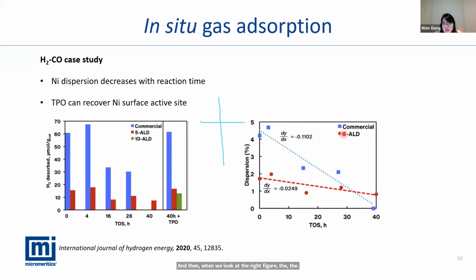So if we look at the commercial one, we are able to see after 40 hours of experiments, the nickel lost all the surface site. That means the nickel has either been sintering, so they lost all the surface site, sintering to very big particles, or has some carbon deposited on the nickel surface. So the customer also did a temperature programmed reduction, temperature programmed oxidation on the deactivated nickel surface. When they were doing the temperature programmed oxidation characterization, they were able to recover the nickel surface here, which all the way goes to the same number as the time equals 0.